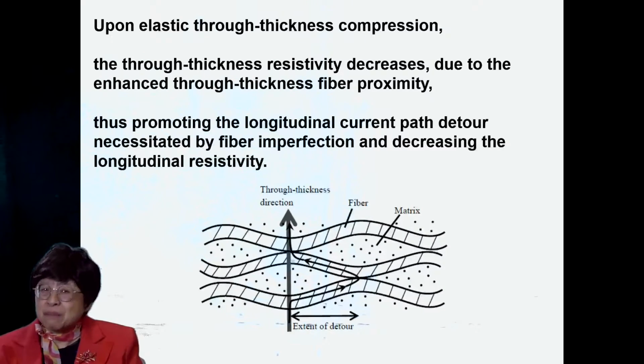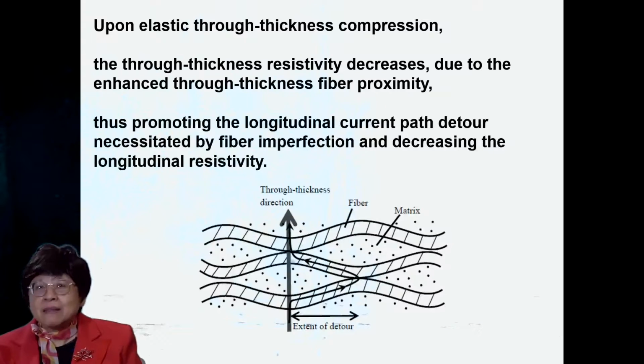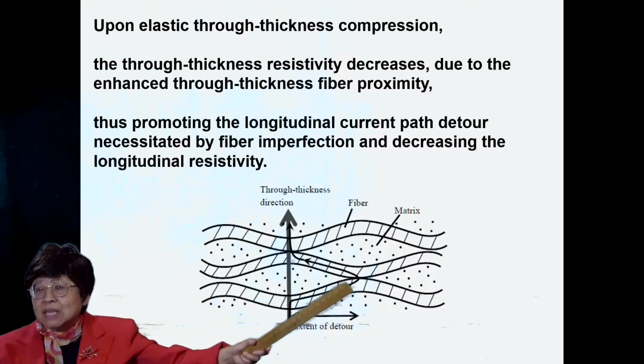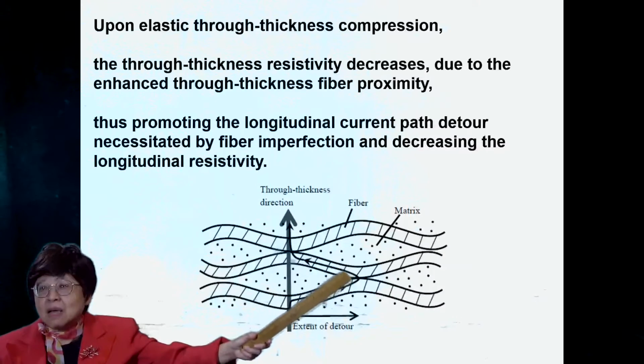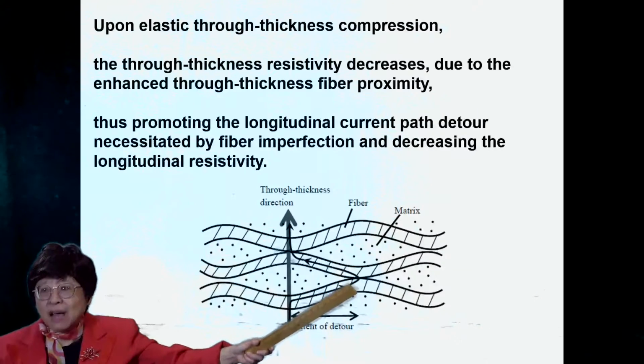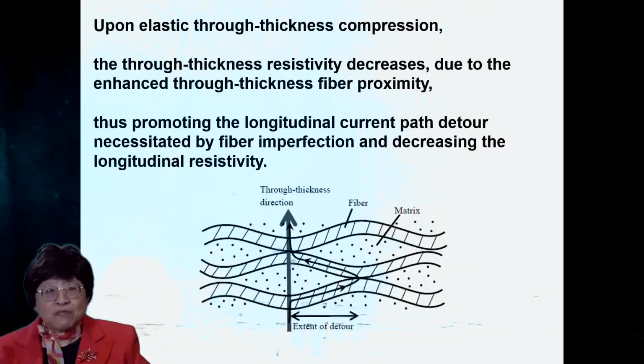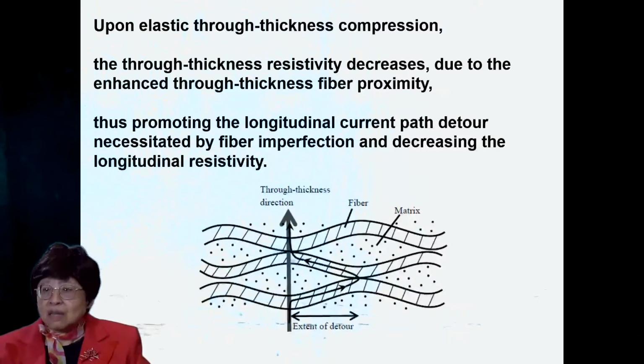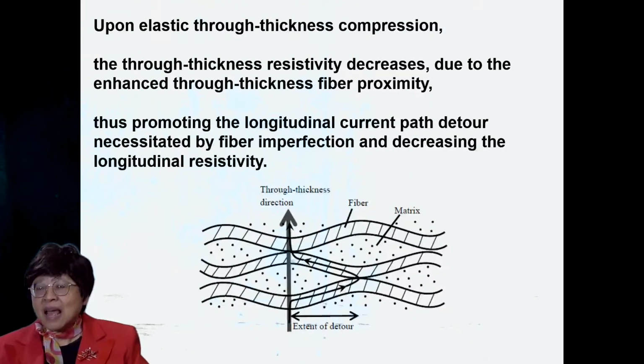That is, there's always some little defects in the fibers, and when a defect is encountered, the current path can detour from one fiber to the next across this interface between the fibers. So if there are more fiber-fiber contacts, this detour would be facilitated, thus decreasing the longitudinal resistivity.